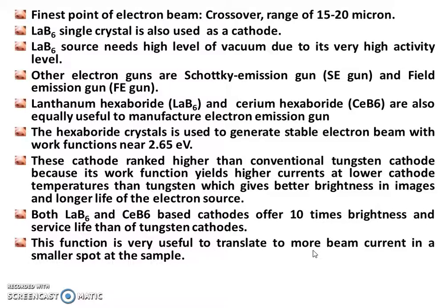Lanthanum hexaboride LaB6 and cerium hexaboride CeB6 are also equally useful to manufacture electron emission guns. The hexaboride crystal is used to generate a stable electron beam with a work function of nearly 2.65 electron volt. These cathodes rank higher than conventional tungsten cathodes because their work function yields higher currents at lower cathode temperature than tungsten. Both LaB6 and CeB6 based cathodes offer 10 times higher brightness and service life than tungsten based electron guns. The function is very useful to translate to more beam current in a smaller spot at the sample.